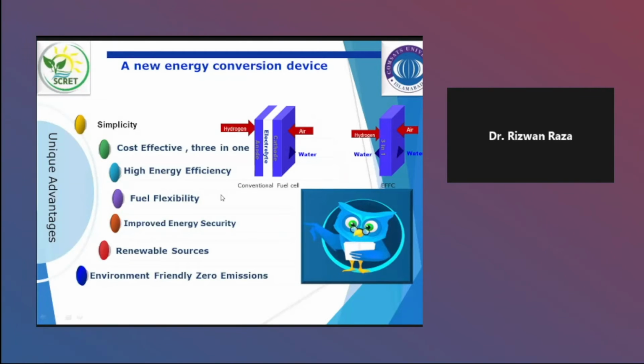After that, that was about the conventional SOFC, which has three layers: anode, electrolyte, and cathode. Another thing, as I mentioned, when there are three layers, there are chances for the polarization losses and ohmic losses as well. But if you can reduce these different components, from anode, electrolyte, cathode, actually we introduce one composite material which can give you three kinds of properties: as an anode, as an electrolyte, and as a cathode. Actually, it is a mixed ionic and electronic conductor, both behaviors. It has ionic conductivity as well as electronic conductivity because it's a composite of both kinds of conductors.